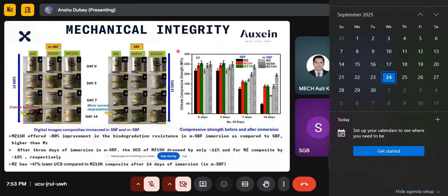So the cracks were also very few in the modified simulated body fluid as compared to the simulated body fluid. I mean, this one is with serum and this one is without serum. So the cracks were fine. So we see that it will not degrade too fast inside the body as compared to the very corrosive environment. This is, we can say, the worst case scenario which we have taken.